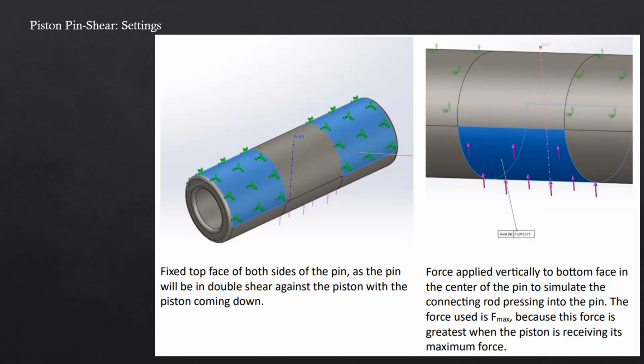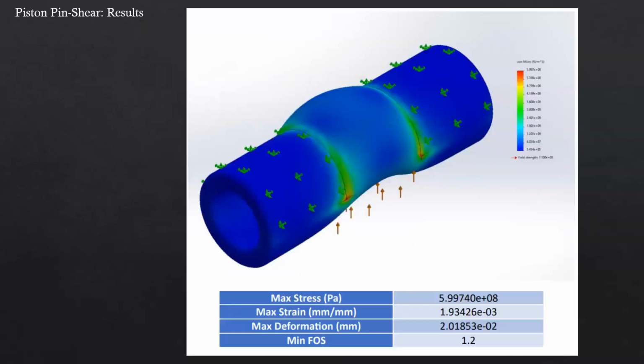And we ultimately found AISI 4340 steel was the appropriate one with a 3 millimeter wall thickness. That ended up giving us a minimum factor of safety of 1.2, which is just above where we wanted to be. Ideally, we would have wanted to be closer to 2, but this does work for our application.